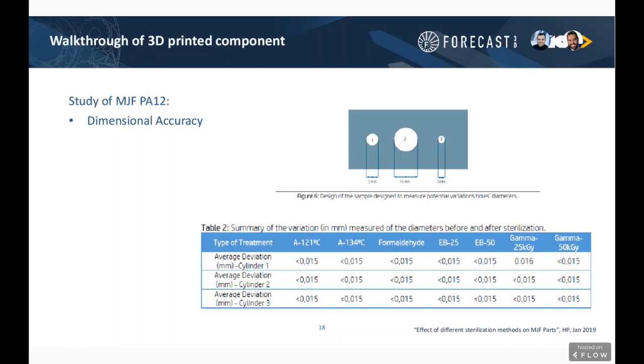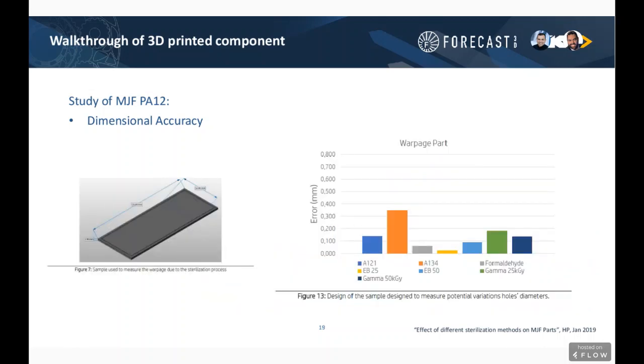Where we see a little bit more interesting results is when we look at the warpage of a part. And this is where the design aspect really comes into play: designing parts so that maybe they aren't as susceptible to these warping conditions, or they're being used in applications where the warp doesn't matter as much. So essentially a design coupon was created, a relatively flat, long part, because that warps the most and becomes easier to measure. And then it was run through the various conditions. Essentially what it's suggesting is as there's more moisture and more heat applied, there's a little bit more warp.